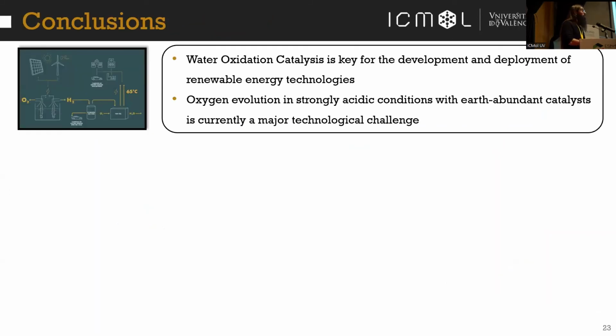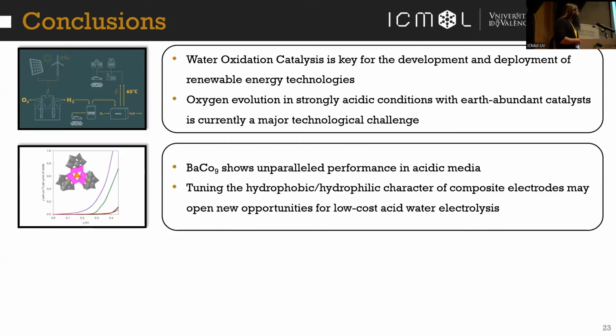So as a conclusion, I hope I showed you that water oxidation catalysis is key for the development and deployment of renewable energy technologies, and that oxygen evolution in strongly acidic conditions with earth-abundant catalysts is a current major technological challenge. Also that the barium salt of cobalt-9 shows unparalleled performance in acidic media, and that's important because this will help to develop more catalysts that would not otherwise be stable in acidic conditions.